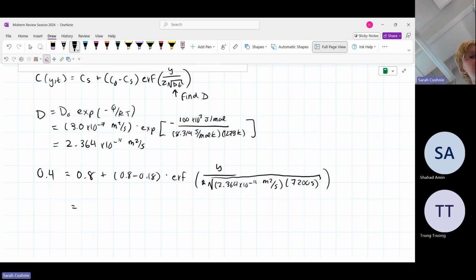So if you calculate this, I actually did this slightly differently on my test, but I don't like the way I did it. So you're going to end up with 0.4 is equal to 0.8 plus 0.62 times the error function of Y over, we'll put in the positives, 1211.937Y.